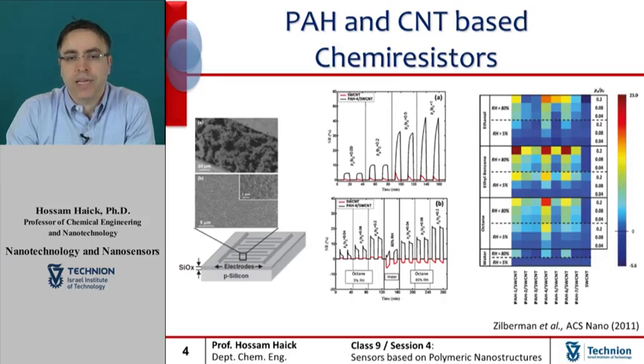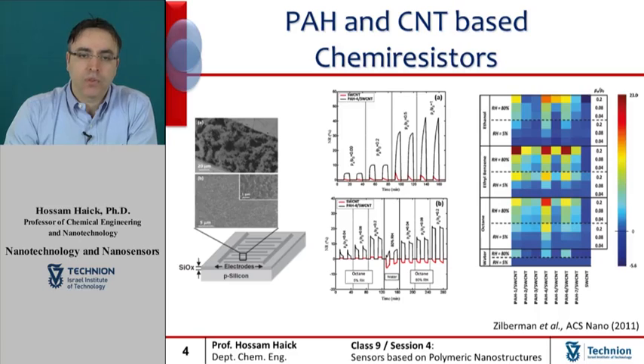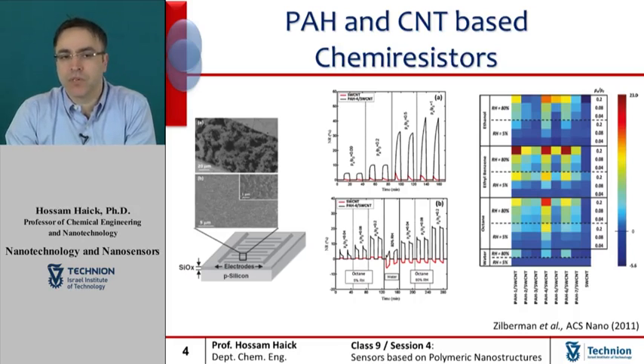From the figure, one can see that although the incorporation of the PAH slightly increased the sensitivity to humidity, it substantially improved the sensing signals towards part or all of the tested volatile organic compounds as compared to the pristine single-walled carbon nanotubes. The higher the volatile organic compound concentration, the higher the detection improvement.